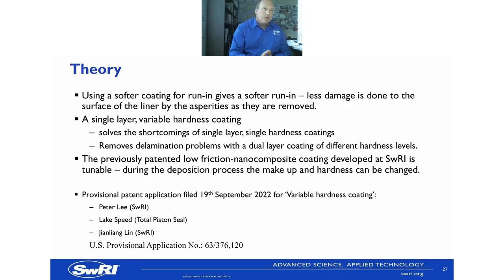Now, we'd already previously patented our friction nanocomposite coatings, and we went down to the materials lab and coatings lab and spoke with the technicians and engineers down there and said, we already know that we can take this coating and we can make it different, because we did that 12 times in the previous IR. Well, what if you can change the deposition of the coating during the coating process? So basically dial it in from a hard coating over to a soft coating right at the end and see whether that has the effect we're looking for.